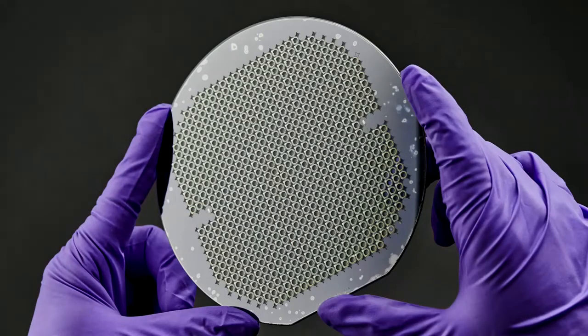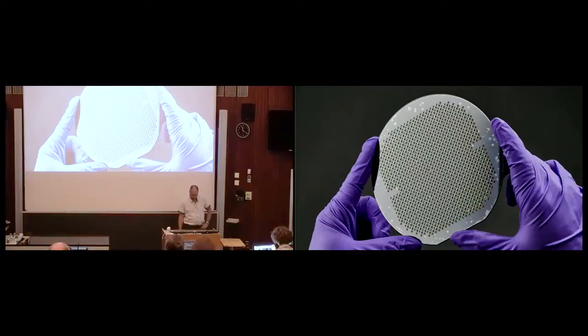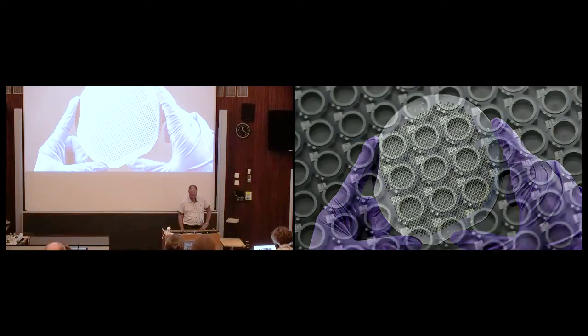So here you see a 150 millimeter diameter wafer that was realized in this process. In this case these are cells for the atomic clocks, which measure 4 by 4 millimeter in size, and here we have more than 700 cells on one single wafer.